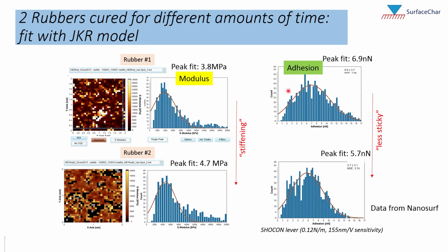And the adhesion showed that the second rubber became less sticky than the first. So we see the expected stiffening and reduced stickiness as a function of this curing process for the rubber, which I could measure quantitatively with these force maps. And again, it was rubber, and I used a JKR model to fit all the data.